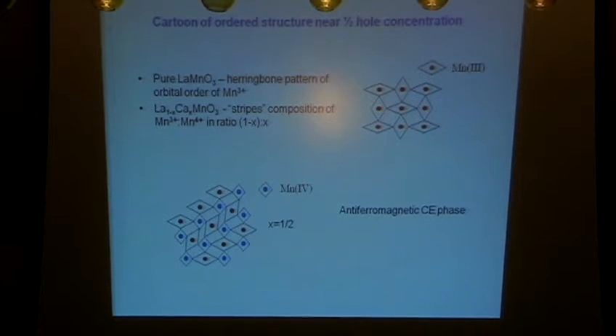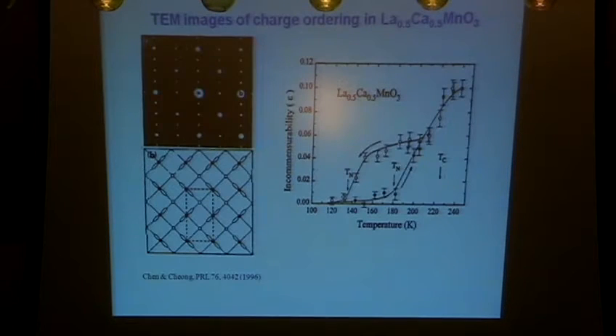So if you dope this material to 50-50 lanthanum calcium, then if you were an engineer, this is the structure that you would make for that, because now you've got 3 plus and 4 plus. The manganese 4 doesn't have this orbital occupied, and therefore it's much smaller and likes to be in a sort of cubic environment. And the way you stack all of these things up is to line them along in sheets like this, alternate rows of 3 plus and 4 plus. And this phase actually will be naturally, it turns out, of course, an insulator, as with LaMnO3, but this will be an antiferromagnet, and it produces what's called the CE phase of the antiferromagnetism. And one can understand that quite readily. So that's what one expects to see.